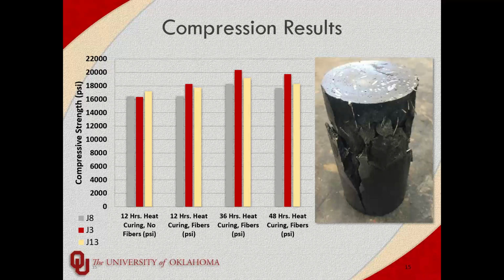But one thing we also noticed, which we thought was a little strange, is that after 36 hours of heat curing, at 48 hours there was a slight drop in the strength, which we thought maybe indicated an upper bound: that if you heat cured it too long, you could start either damaging it or maybe just drying it out, which could cause issues either way. So we decided to stick with a 36-hour heat cure for our study, and that was the recommendation we gave to ODOT. Next slide.